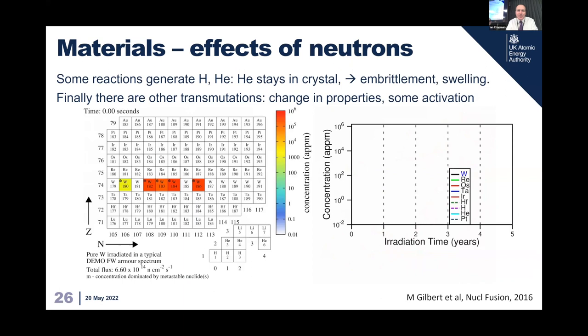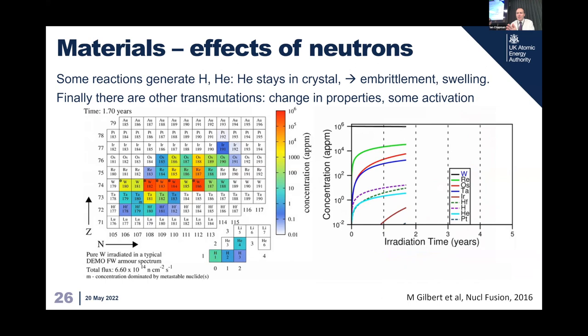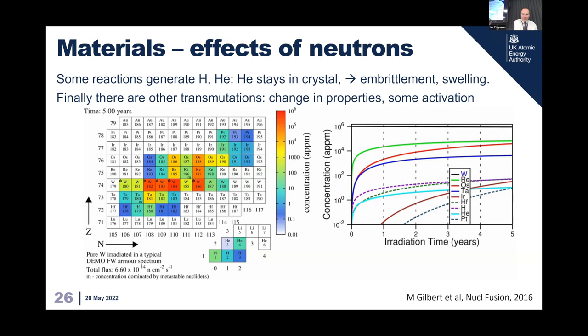The other things which happen are that you get transmutations in the elements. So what we put in the armor, say pure tungsten to start with, as those displacements happen, the chemical properties and the mixture will change and you'll get different isotopes appearing. You'll get in that tungsten quite a lot of rhenium and osmium and various other things. We also produce helium when fusion happens, right? That helium then gets embedded into the material and that will cause embrittlement, it will cause swelling.